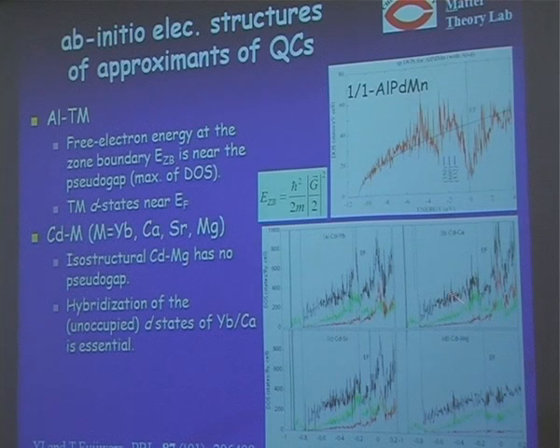So what's the difference between these? All of these systems are isostructural. The only difference is the second element. And I show the partial density of state of the d component from the ytterbium, calcium, and strontium in red here. So for the magnesium, we have no d state here. So that is the reason why we don't have any pseudo gap at the Fermi level for cadmium-magnesium. So hybridization of the unoccupied d state of ytterbium and calcium is very essential in this case.